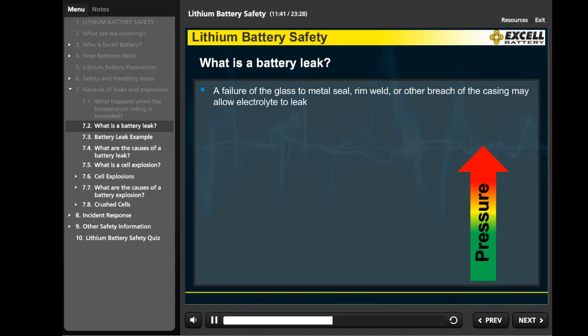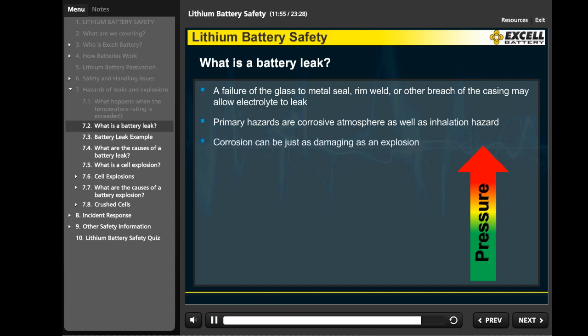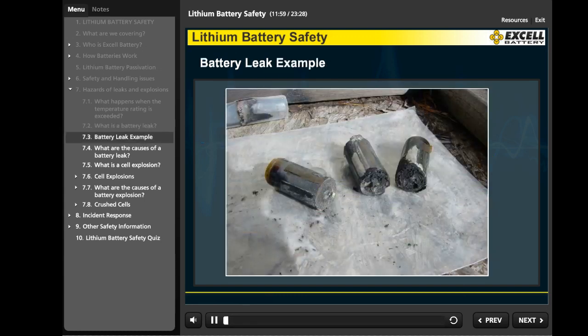If a cell leaks, the primary hazards are a corrosive atmosphere, which will corrode electronics and metal surfaces, and an inhalation hazard that can be toxic to humans. Although an explosion has the added hazard of shrapnel, the corrosion of a leaking battery can be just as damaging to surrounding equipment as an explosion. This is a photograph of a lithium battery that had leaked inside a pressure housing while downhole. The corrosion of the thionyl chloride caused the appearance of the stainless steel casings as seen here.